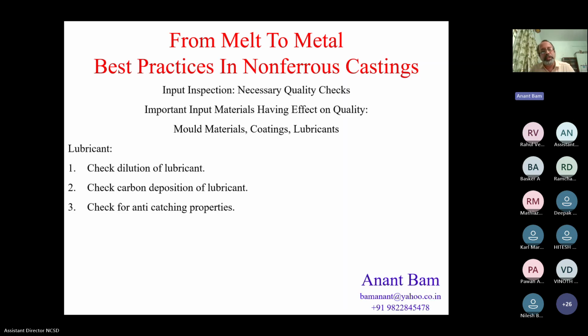So first and foremost, check the dilution of lubricant. And it's very difficult to check the dilution, so you have to ensure a process of making correct dilution of the lubricant. You have to prepare a recipe by which the recommended dilution of the lubricant can be achieved. I have witnessed a case in a very reputed foundry making more than 10,000 tons a month of aluminum pressure die casting.